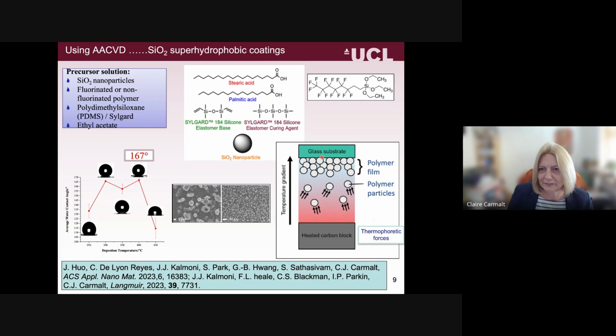But to overcome some of the adherence problems, what we did was to add in polydimethyl siloxane, or Sylgard, which are shown here. And that just acts to help as a sort of glue, to help it adhere better to the glass surface. And you can see this is the SEM of our resulting films, and you can see a nice rough morphology. And we looked at the deposition under different temperatures, so between 250 and 450, and between 300 and 400, we were getting super hydrophobic water contact angles. So that was good, and our adherence was quite good. Sorry, the solvent we used was ethyl acetate.